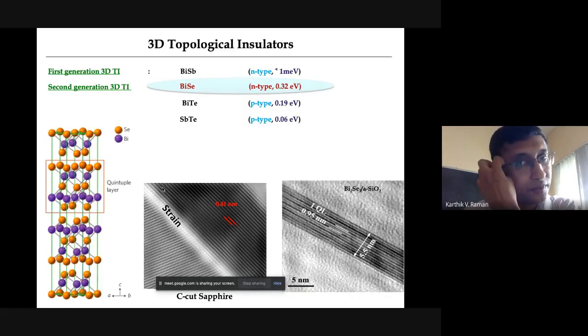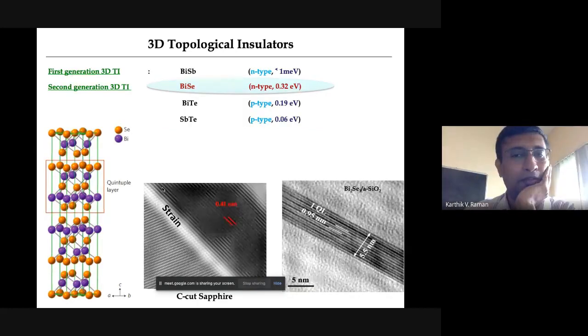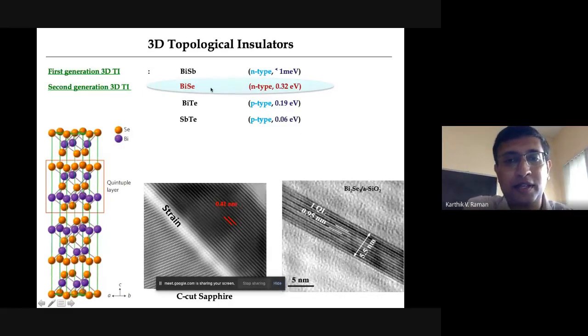Okay, so we're talking about topological insulators. They're primarily a different kind of materials. What we have worked on is bismuth selenide and recently bismuth telluride. These are materials which basically consist of quintuple layers, which are layers of bismuth and selenium. Between two quintuple layers, both ending with selenium, there is a van der Waals coupling between the two selenium layers, and therefore each quintuple layer is somewhat unique to the system, and three quintuple layers form a single unit cell of your system.